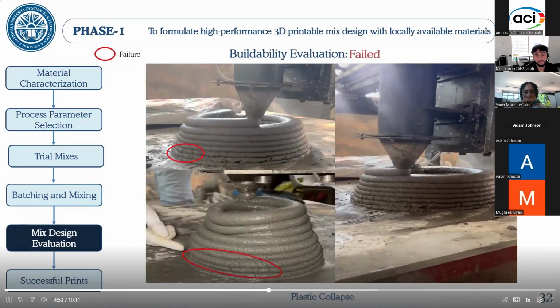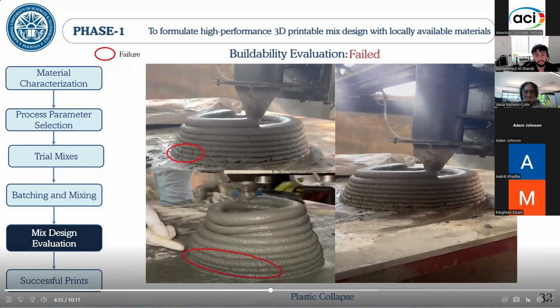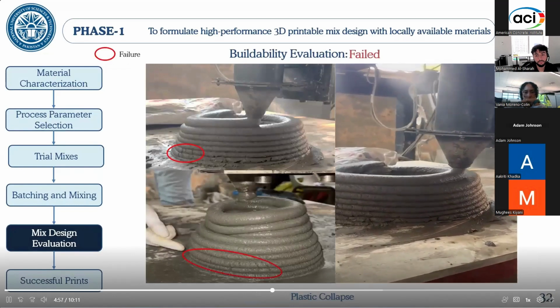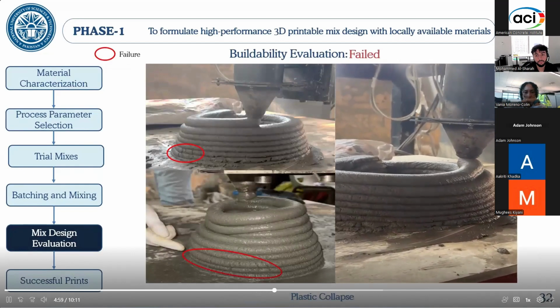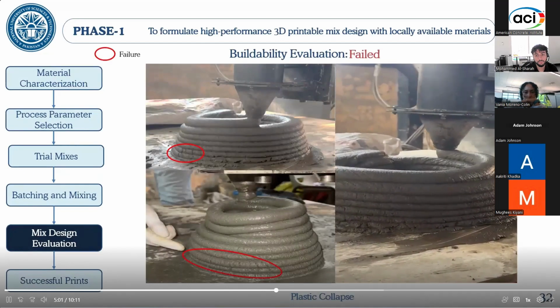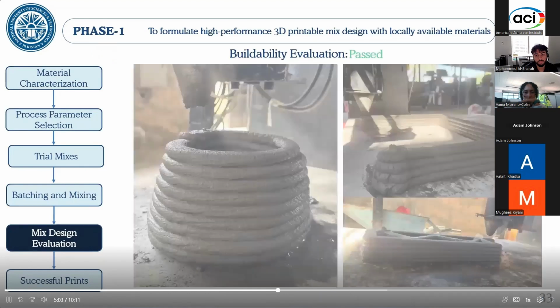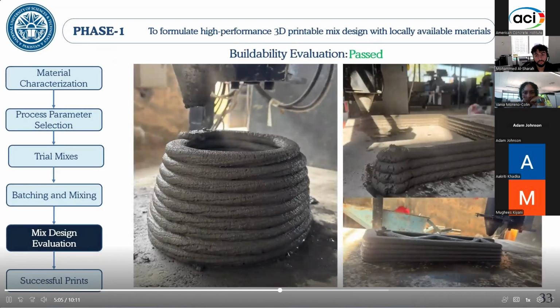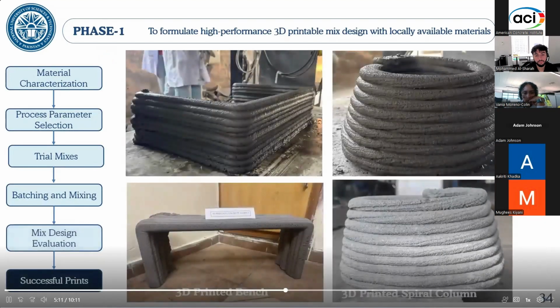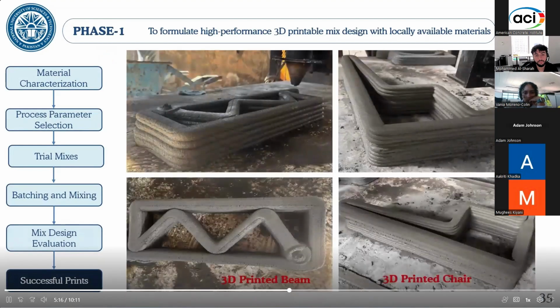Again, this print failed in terms of buildability, this time due to another phenomenon known as collapse. The bottom layers have essentially flattened under load due to insufficient yield stress of the mix. Now these are some successful prints. As can be seen, layers are fairly uniform and stable. These are some more members which have been extruded successfully, and again some more successful prints.